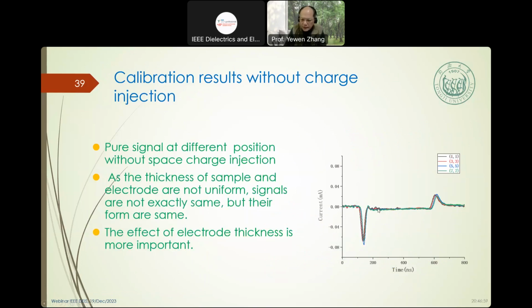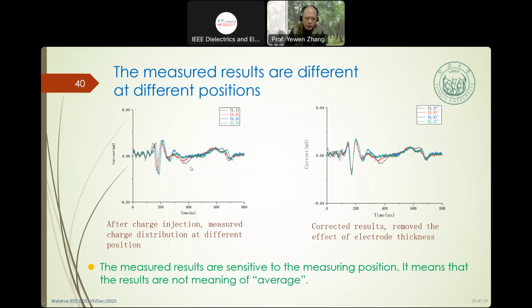So we get a different space charge. See, the peak is also different. The signal at a different position without space charge injection, as the thickness of the sample and the electrode are not uniform, is not exactly the same, but the form is the same. The effect of electrode thickness is more important. So after applying voltage, we can find the peak is different. After the charge injection, in the measurement at a different position and the corrected result, we moved a little bit here to remove the effect of thickness. So the measuring result is sensitive to the measuring position, which means the result is not uniform, not an average.